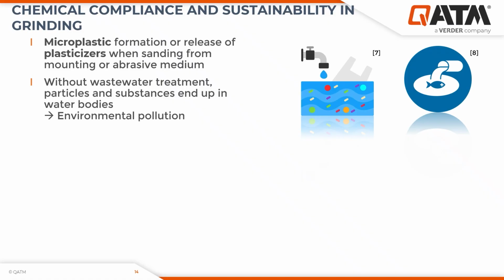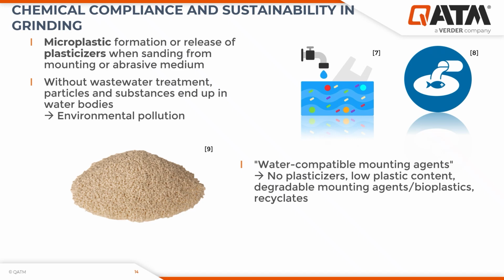However, depending on your needs on your mounting and the following preparation steps, a company or a lab can try to substitute it with so-called water-compatible mounting agents, which either do not contain any plasticizers or have rather low plastic content. For example, if you have a higher filler content, or the filler is composed of not plastic compounds but more cellulose compounds, so degradable compounds, if the mounting agents are overall degradable or based on bioplastics, or at least if these compounds that you are necessarily grinding down are based on recycled material, in order to improve the overall environmental profile of your system or of the mounting resin.